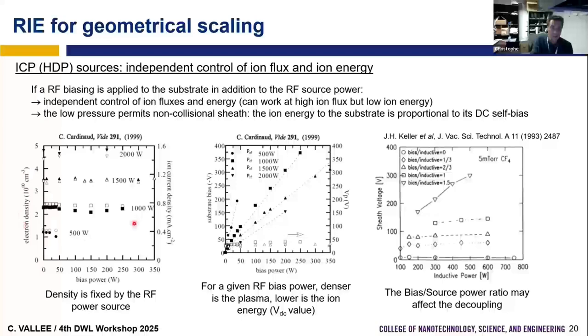You can see that, for example, here you have the plasma density. If you increase the source power, so the power applied to the coil, you increase the plasma density. But if you increase the bias power, to increase the ion energy, you do not modify the plasma density. So the bias power has no impact on the plasma density, so the ion flux, but the bias power will have an impact on the DC self-bias voltage, so will have an impact on the ion energy.